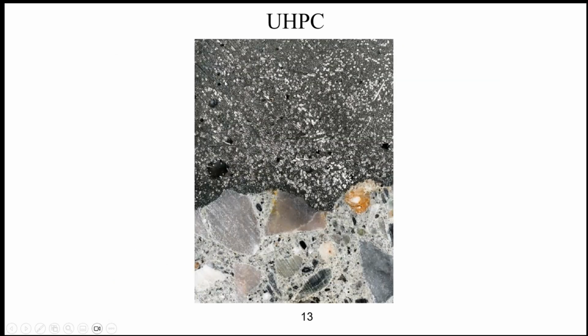Those of you who have not seen this slide: the upper portion shows the UHPC, and the bottom shows the conventional concrete. When you apply the UHPC to conventional concrete, you must prepare the surface adequately. By adequate I mean you need to have exposed concrete, exposed aggregate. That's what, for example, Sam was saying, that they sandblasted. And number two, you have to make sure that the surface of the material is moist before you apply the ultra-performance concrete.